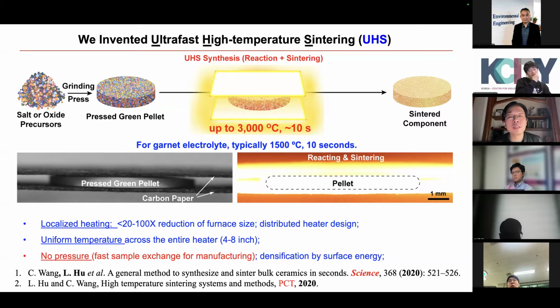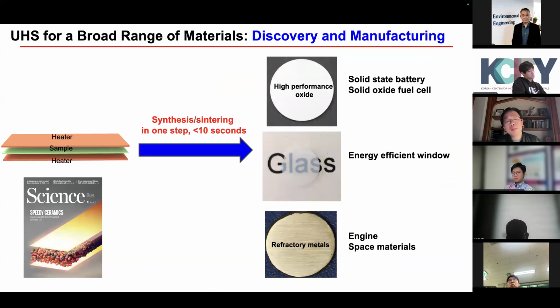So you basically lock it in the structure, and we don't use pressure. I hate using pressure because if you're using pressure, it's very hard to change samples, so that's not good for manufacturing. No pressure means you can change samples very quickly. So with this platform, with a heater on top and a heater on the bottom, you put the sample in between, or sometimes just the heater on top with no heater on the bottom. You can just scan the heater over your coating or sample. You can make ceramic materials, glass structures, and refractory metals for jet engines.